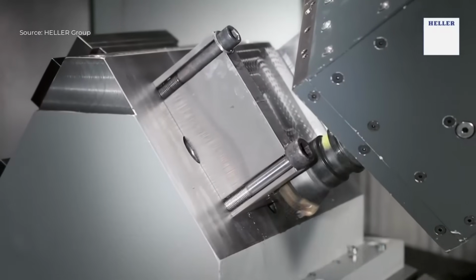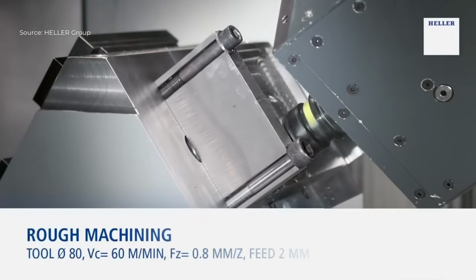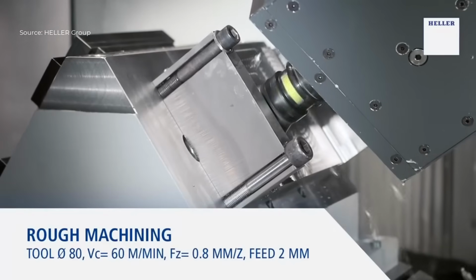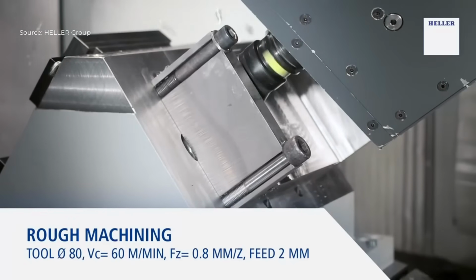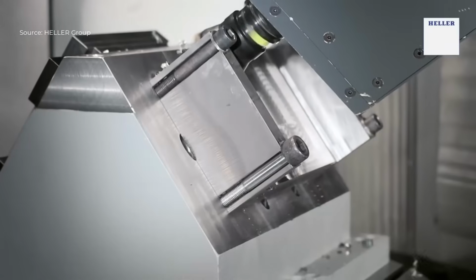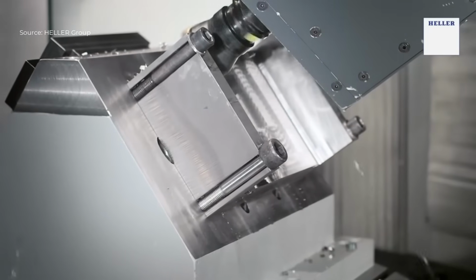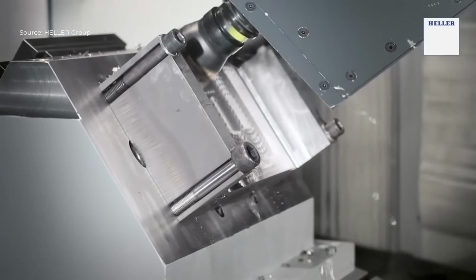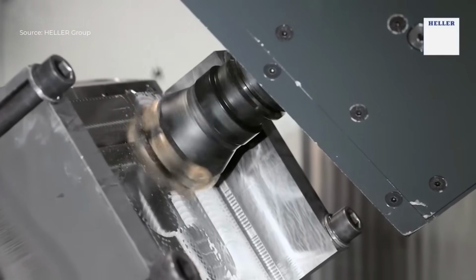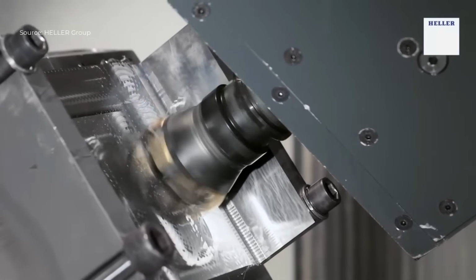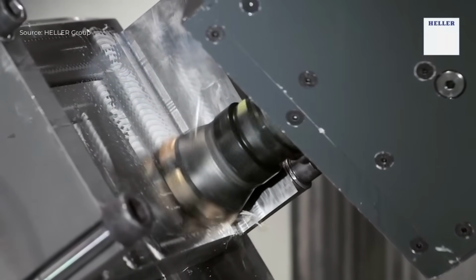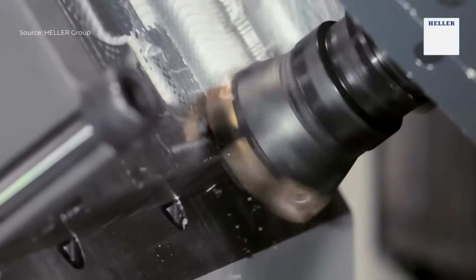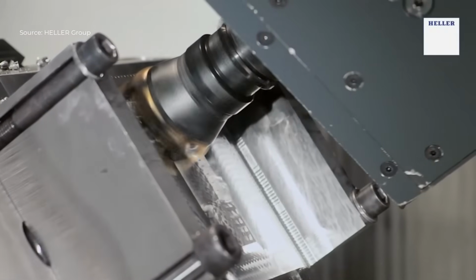The Hellerfort 4000 performs 5-axis simultaneous machining of a titanium Ti6Al4V aerospace component. Rough machining is carried out using a Ø80mm tool at a cutting speed, VC, of 60 meters per minute, feed per tooth, FZ, of 0.8 mm/Z, and a feed rate of 2 mm. This removes bulk material efficiently.